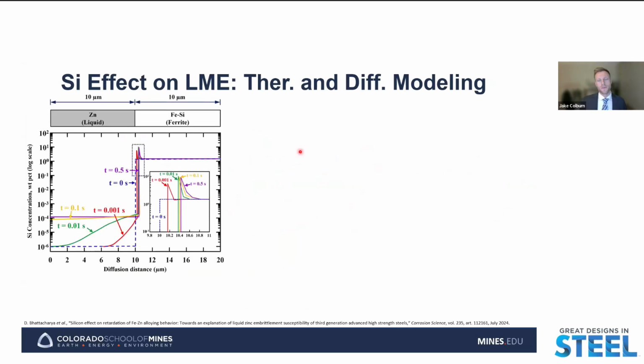And so if we want to understand a little bit more about potentially why we're seeing the difference in behavior, the difference in ductility, the silicon enrichment, we can begin by doing some thermodynamic and diffusion modeling. And so here on the left, we have a diffusion couple of liquid zinc on the left side, silicon-containing iron on the right side. And this is a diffusion calculation up to 0.5 seconds. And so we see that as time progresses, there is silicon enrichment at the interface.